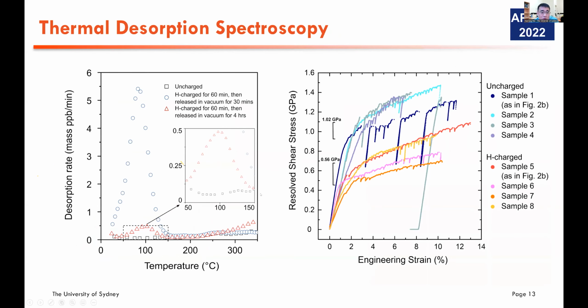So to double check the results, we performed thermal desorption spectroscopy to simulate the in-situ compression experiment after hydrogen charging. The black squares here are uncharged pearlite, and the blue ones are hydrogen charged for 60 minutes and then released in vacuum for 30 minutes, which is the earliest time, the quickest experiment we can do. And even after we set up the in-situ experiment and the sample rested in the SEM for around 4 hours, there is still a significant amount of hydrogen left in the sample, which implies that the mechanical property difference we observed is due to the hydrogen in the material. We also repeated the experiment to show that this result is repeatable.